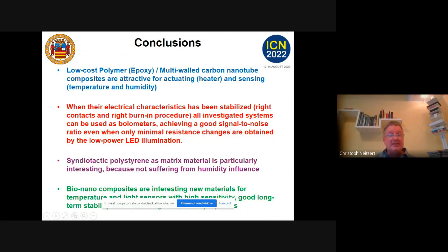Syndiotactic polystyrene as matrix material is particularly interesting because it does not suffer from humidity. So you don't have changes imposed by the light itself. By external ambient temperature, yes, but not by the light itself, if it's low intensity light. Bio-nano composites are interesting new materials for temperature and light sensors with high sensitivity and good long-term stability. Good long-term, we remeasured them after 5 years, and they were still stable working. And without the nanotubes, the cells would just be dust. So we could make a stable bio-nano tissue, which has optimal sensing characteristics.